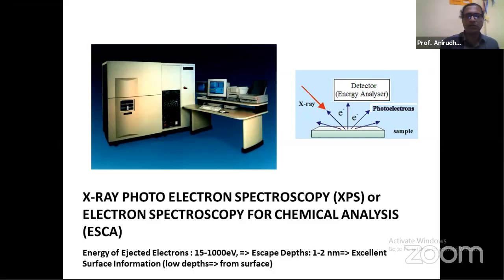Now, the energy of those ejected electrons from the surfaces is usually less than 1000 electron volts. If they manage to escape from this surface, then calculations have shown that these escape depths are nearly 1 to 2 nanometers, because these are not very high energy electrons. Since they are weak, they cannot emerge from the bulk. Those which start in the bulk would get absorbed in the matrix itself. They won't come out of it. So those which manage to emerge from this surface could be from depths not more than, let's say, 2 nanometers from the surface.